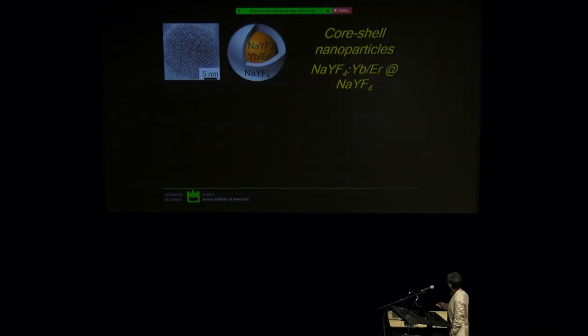Nanoparticles, we would say nowadays. And so we thought, can we do it with our nanothermometry measurements? So we basically took these extremely bright core-shell nanoparticles, fluoride with a core of yttrium, and in the periphery of the core we have also doped with ytterbium and erbium, and then there is a shell of yttrium, which is inert, but it just protects from the outside world.